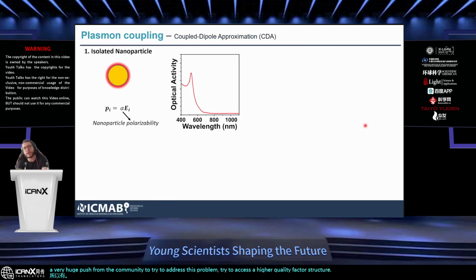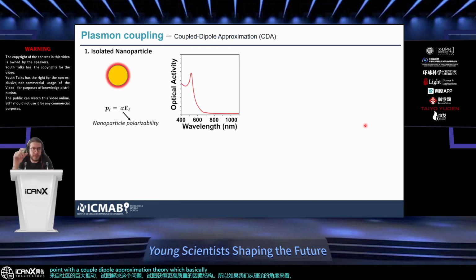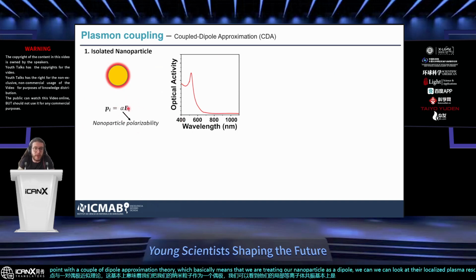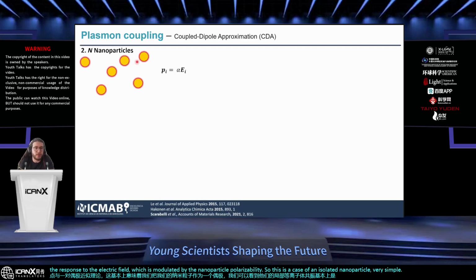And so if we look at this from a theoretical standpoint with the coupled dipole approximation theory, which basically means that we treat our nanoparticle as a dipole, we can look at its localized plasmon resonances basically as the response to the electric field, which is modulated by the nanoparticle polarizability. So this is the case of an isolated nanoparticle, very simple.